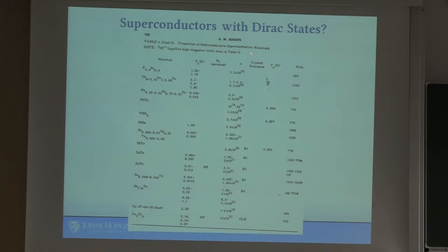Rather than say, what are topological insulators and how do I dope them to make them a superconductor, I said, let's go the other way. Let's dig out an old table, this is a famous review from Roberts, and he has a whole table that says properties of semi-conductive superconductive materials. Or put another way, he has a table of low carrier density superconductors. And so you scan down the list and you say, which things have heavy elements? And for a reason I'll show you in just a minute, we ended up settling on this compound, thallium-5-tellurium-3. I wouldn't read too much into the specific numbers here other than to say that was the idea. It's got heavy elements, so there's going to be a lot of spin-orbit coupling, and it's a reported superconductor with a low carrier density, so maybe we can do something with it.